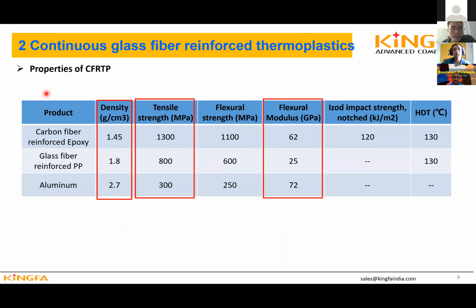So in this slide, we compare three different kinds of properties. The first one is in the BMW i3, they use carbon fiber reinforced epoxy. The density is only 1.45, and the tensile strength is 1300, much higher than steel and aluminum. And the flexure is close to aluminum. So that's why carbon fiber reinforced epoxy can reduce weight, and the strength is much higher than steel. Okay, but the price is very high. It's at least 10,000 rupees per kg. So for some applications, we cannot use this material.